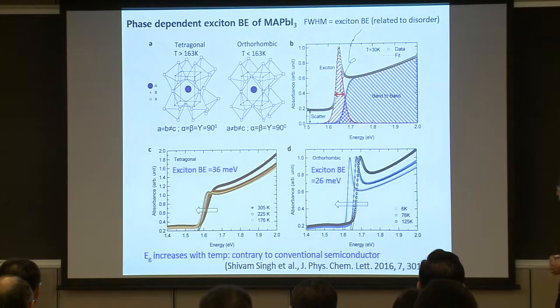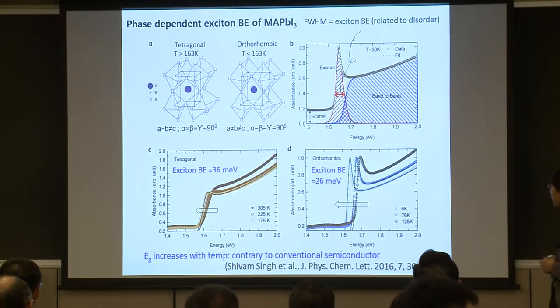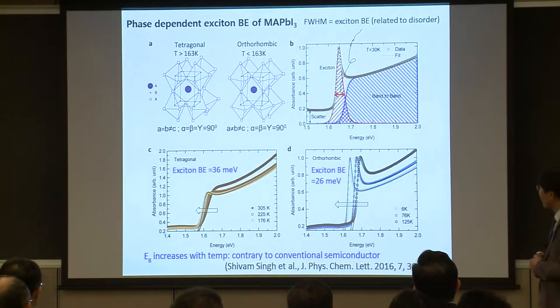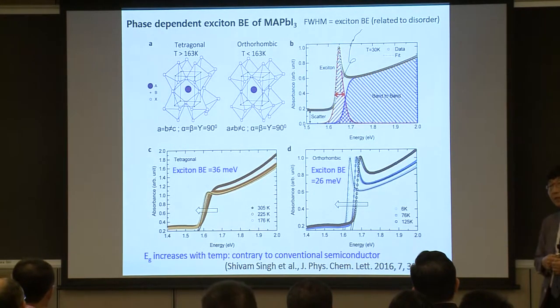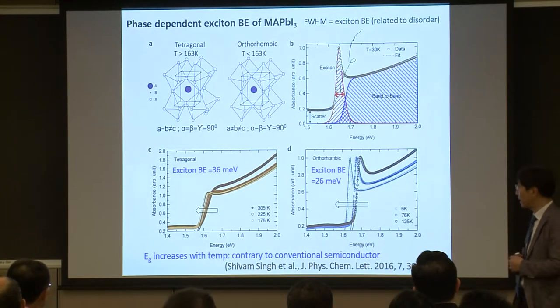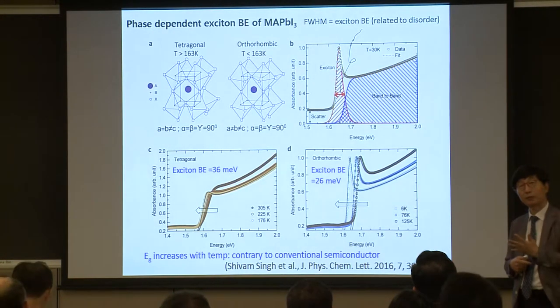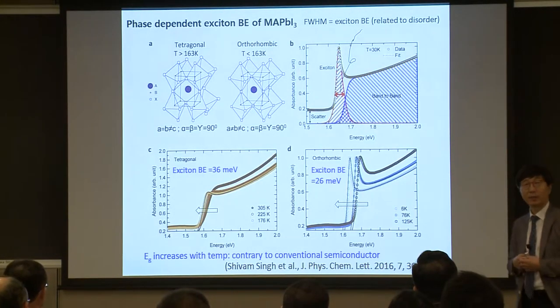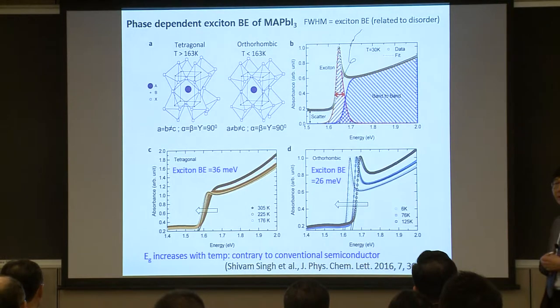And also, for instance, the band gap energy can be estimated in terms of temperature by seeing the exciton binding energy. Usually semiconductor band gap energy decreases with temperature, but in MAPbI3 the band gap energy increases with temperature, which is contrary to the conventional semiconductor. So we have to define this material newly. It's not a conventional semiconductor.